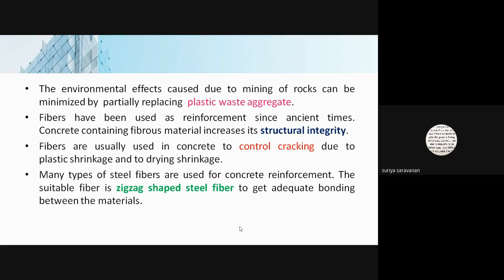Apart from that, we have also used steel fibers. If you take this concrete, it will contain many fibrous materials, and because of the steel fiber, the structural integrity of the concrete can be increased. Moreover, when we use the fiber, it will control the cracking in the concrete. Many types of steel fibers are available in the field, but here we have used zigzag shaped steel fiber, since it has been proved in the literature that zigzag shaped steel fiber gives adequate bonding between the materials.